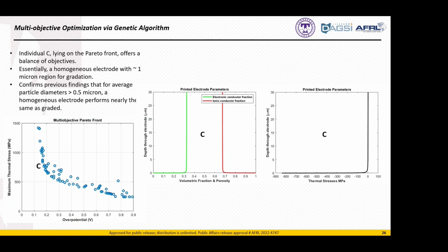But as you can see here for the nickel YSZ, we found that at least the compositional grading is not all that beneficial. But we think that's due to the disparity between the respective conductivities. So you just want to minimize the electronic conductor down to its percolation threshold, and leave it at that. But as far as the porosity grading is concerned, I could see that perhaps being done through a screen printing process. Some of the prints that we've done, we've just broken the electrode up into like 3 or 4 discrete layers and approximated it that way.